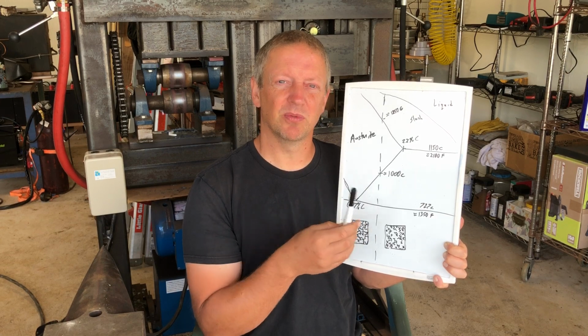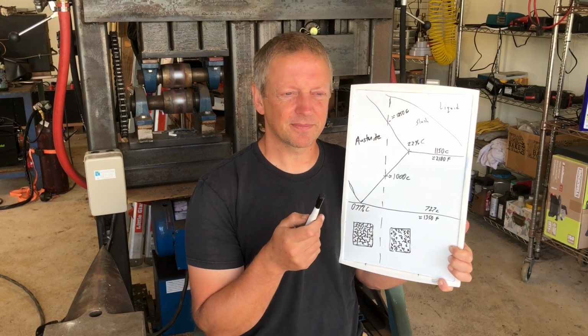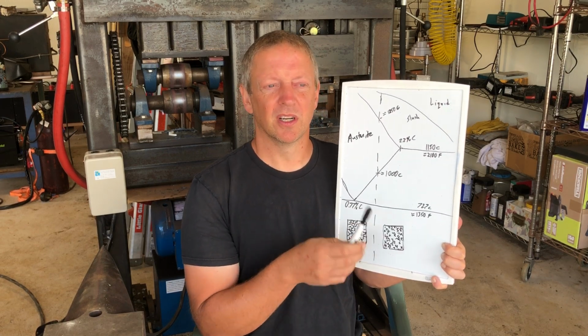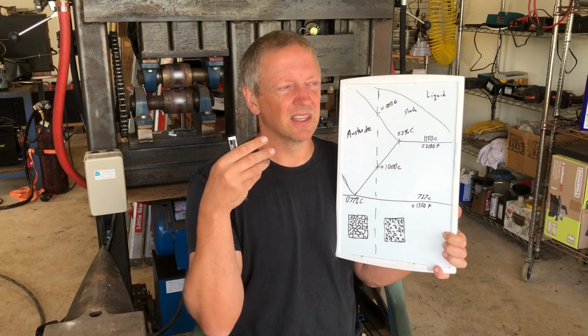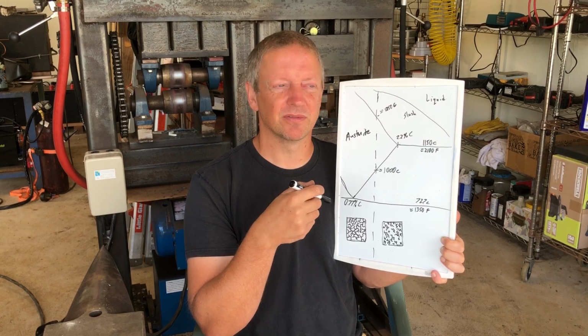Because remember what I said before, there are a few different reasons for carbides to precipitate where they do. You can have them precipitate on austenite grain boundaries, because where the grain boundaries are, the crystalline lattice doesn't line up perfectly. So you get holes or dislocations in the crystalline lattice, a convenient spot to have carbon pop out of solution and make some carbides.